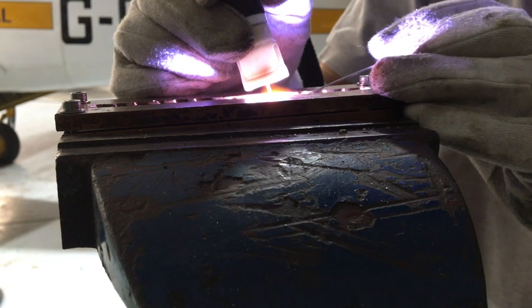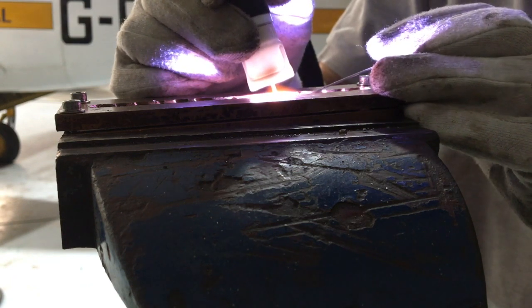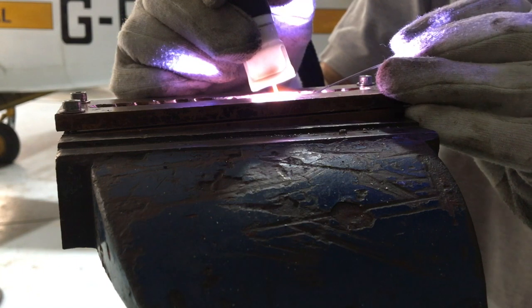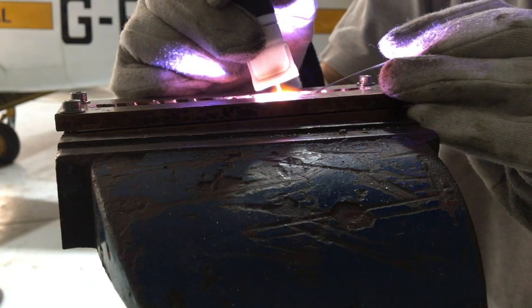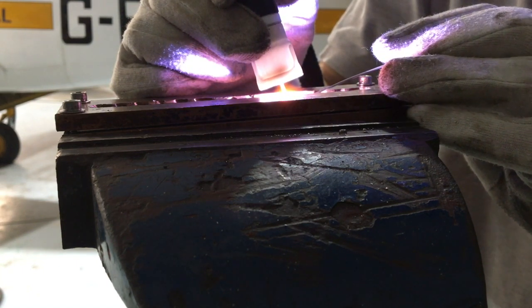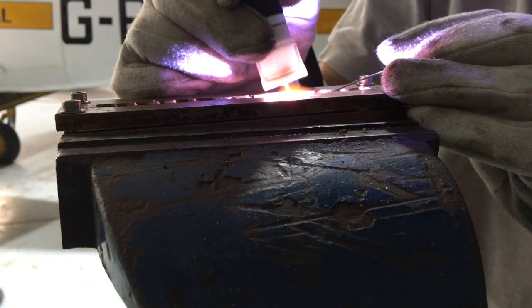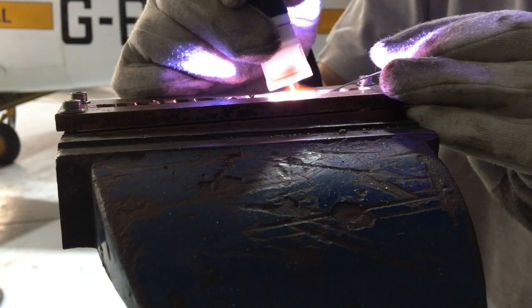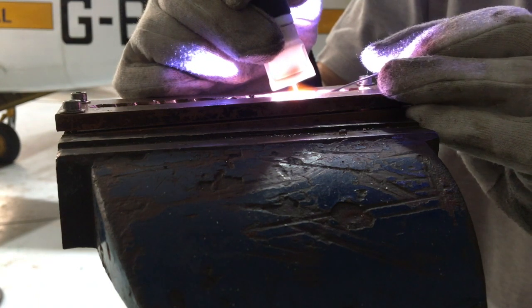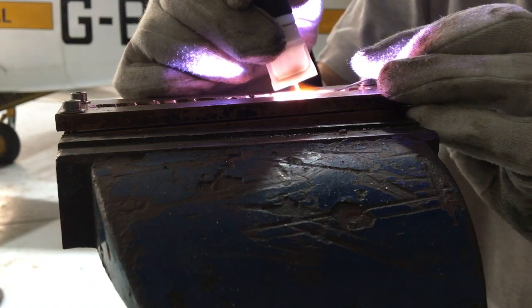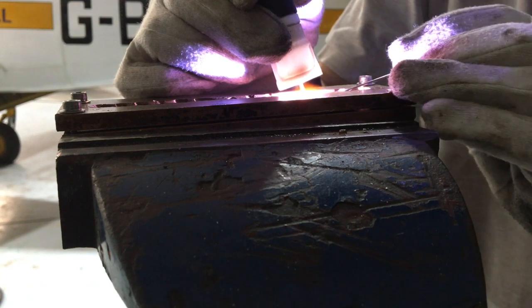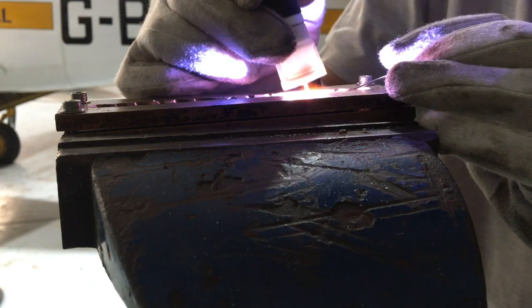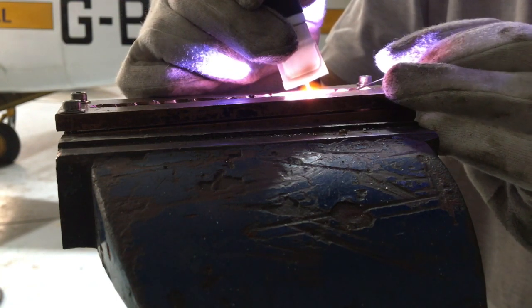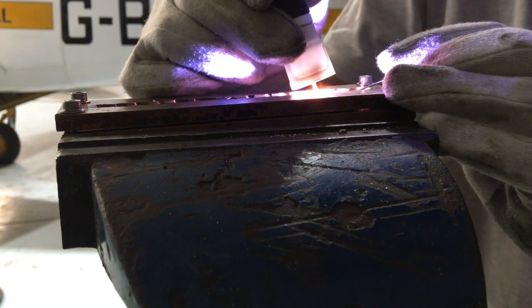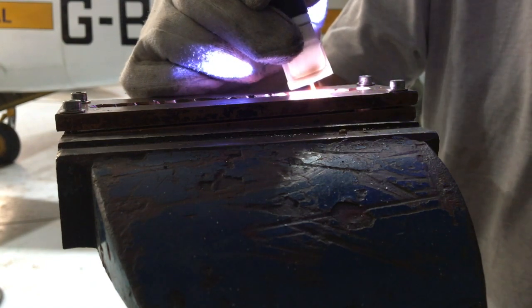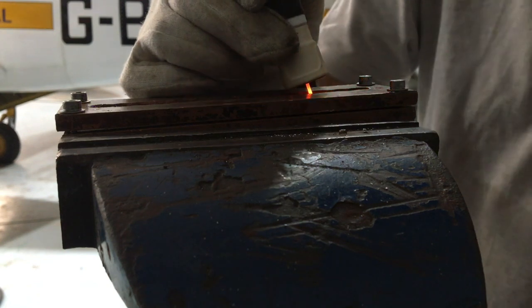I know I did. Things happen quite quickly, so you tend to back off the pedal and try and go slower. That actually results in more heat input, because heat input is a function of travel speed as well as amps. If your amperage is low and you can't get moving, your total heat input can often be higher because of the time it takes to complete the weld. Now we'll get these welds out of here in a minute and just have a look, see what gives.